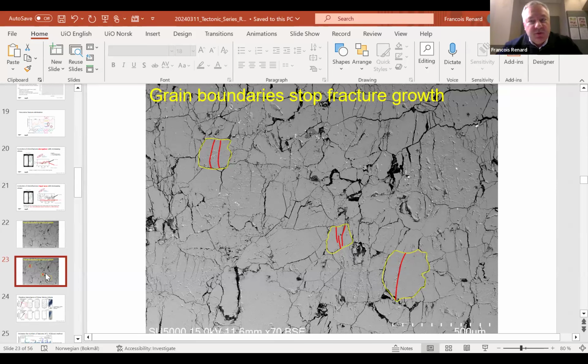So I don't know if you have been working on Carrara marble. Yeah, a bit. So this rock is incredible because it can accumulate a lot of damage before it fails. And that's what happened in this rock. You have some grains and a lot of fractures. It corresponds to the opening inside the grain. And when these two fractures have opened and they reach the grain boundary in yellow, they stop because there is a large energy to cross and break the other grain. So it means that this fracture will stop and it will cost less energy to open another fracture in another grain somewhere else. So for example, here you have an example. We have the same fracture that crossed two grains, but that's quite exceptional.